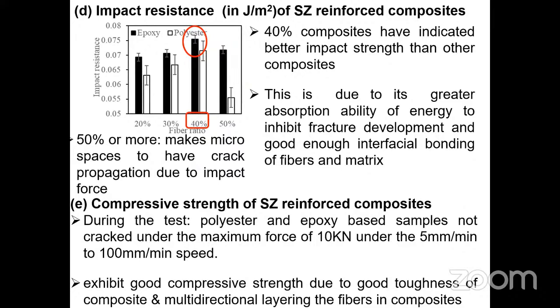When it comes to the compressive strength of Sansevieria reinforced composites, during the test the polyester and epoxy-based samples did not crack under the maximum load of 10 kN, because it has good compressive strength and the composite has fiber layers.